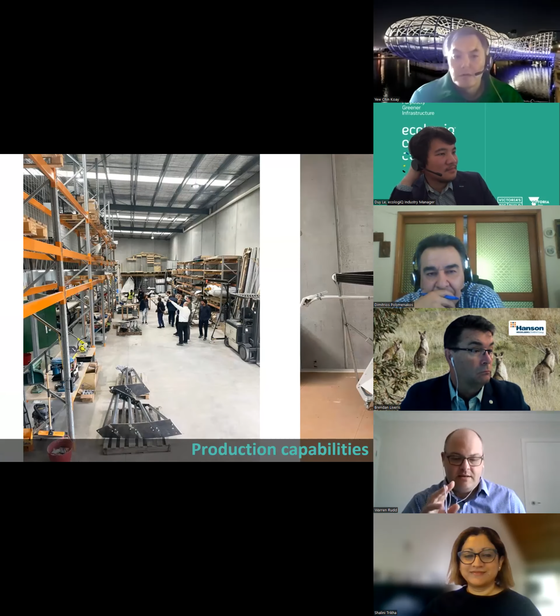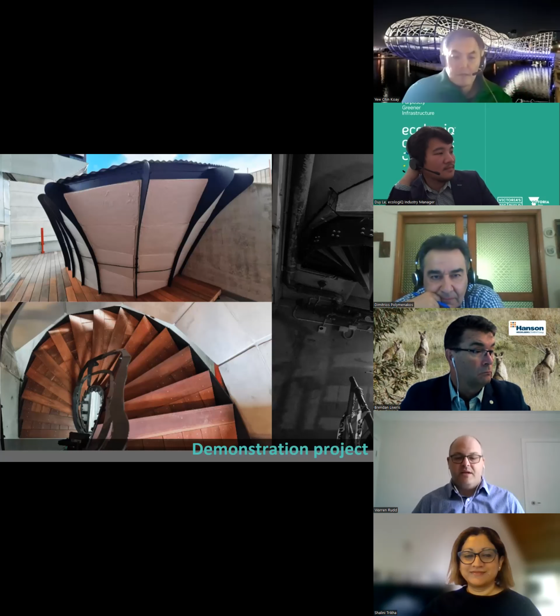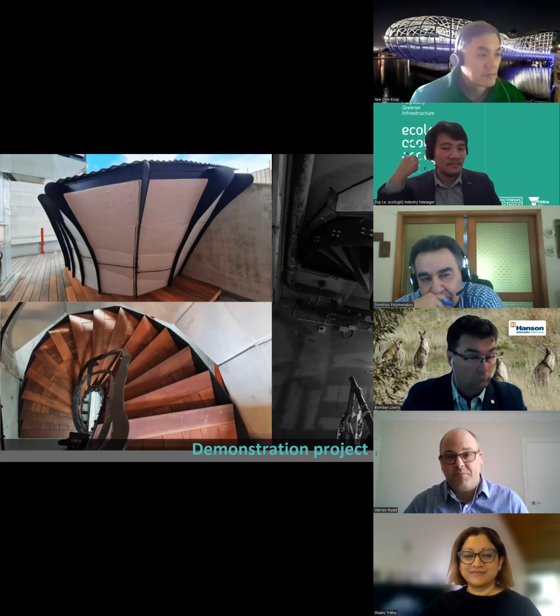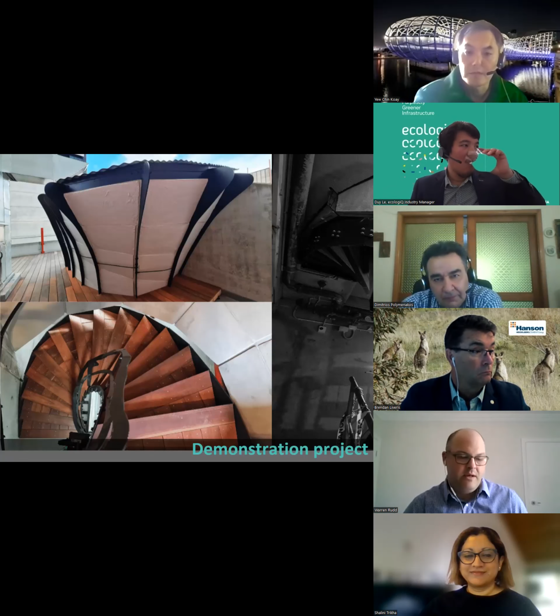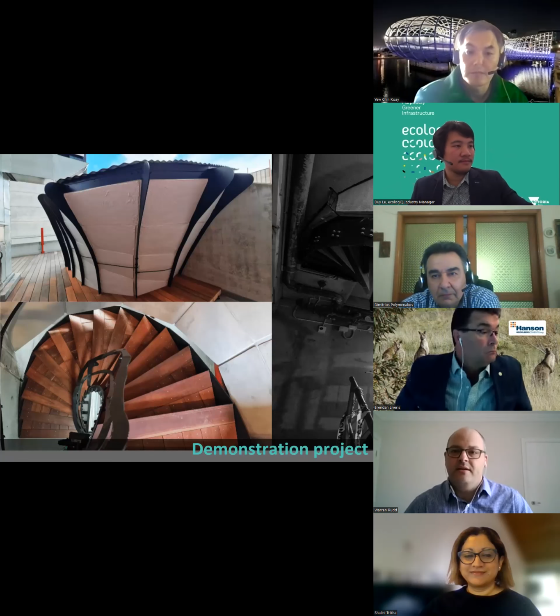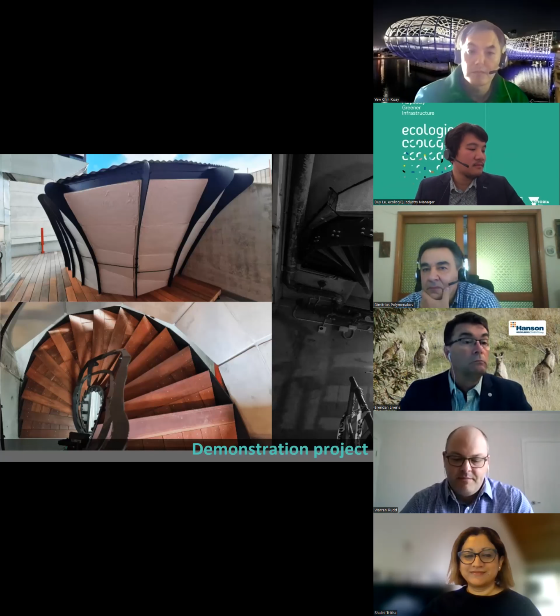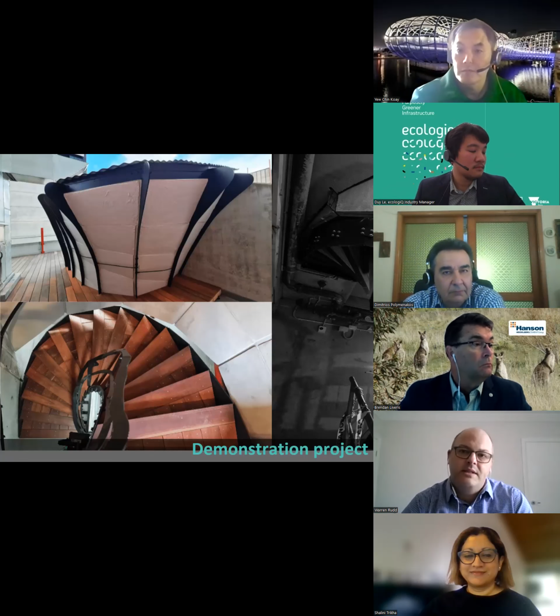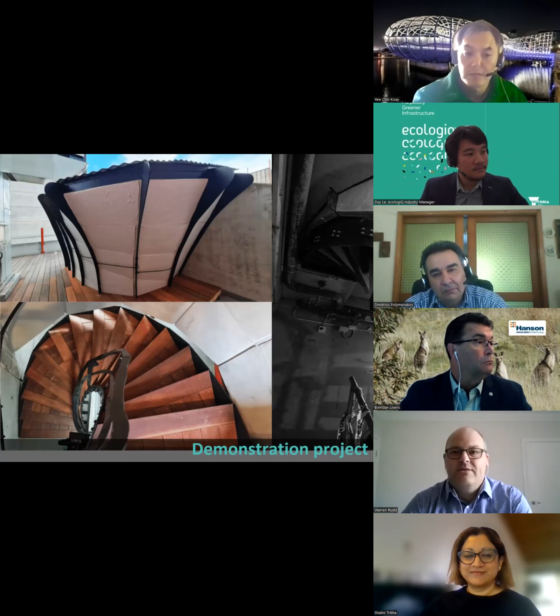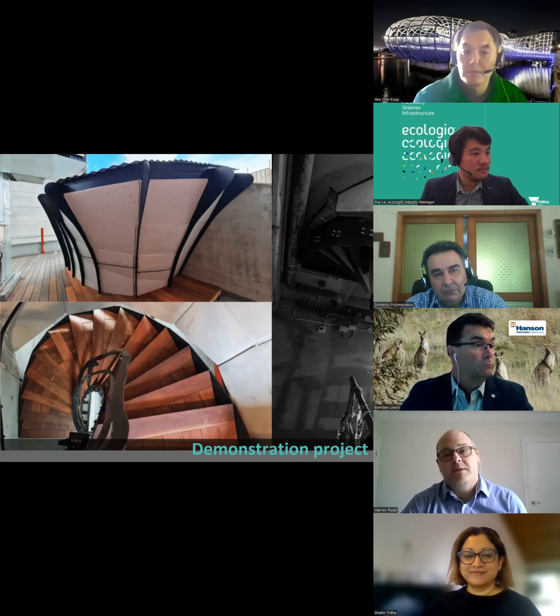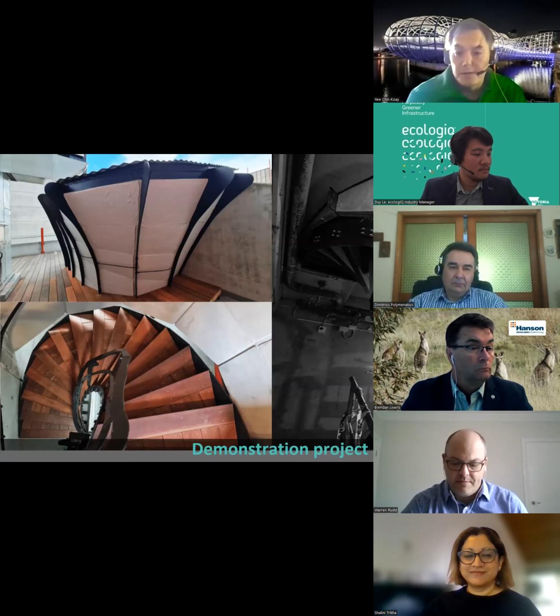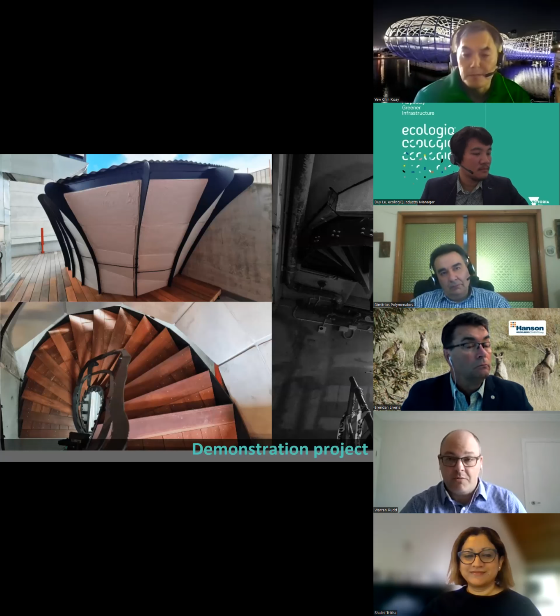If you just go to the next slide. Previous slide. So some of the highlights from this project were, we achieved a pretty intricate design. When we first tabled it, people were scratching their heads to work out how it was actually possible, but we achieved it. We eliminated all the formwork waste, a 100% reduction in formwork waste in the casting process. We achieved an 80% reduction in CO2 emissions using our geopolymer mix compared to a standard Portland cement mix. We were able to achieve a 13% reduction in steel usage. You can see those ribs, they were part of the design. We achieved a non-combustibility certification on the panels, and we achieved engineering compliance and sign-off.